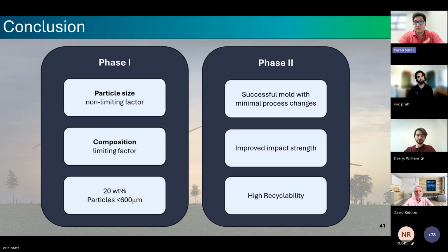And we found that our blend had greatly improved impact strength from the material currently in use, had a high level of recyclability, and more importantly, we found that our project plan and process is in fact industrially scalable with our successful molding trial of multiple cable spools.